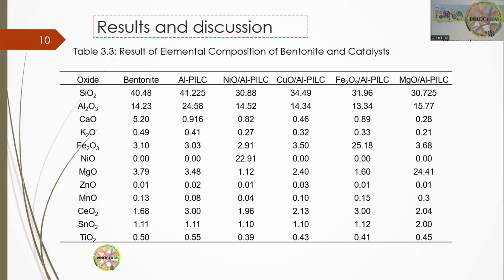This is the elemental composition of the bentonite and all other catalysts. Aluminum oxide and silica, which are the main constituents of the montmorillonite, have been observed. Then we have calcium, which is about 5.20. Because of that, we don't even have the presence of sodium, so we classify this bentonite as a calcium bentonite. And the high percentage you are seeing in nickel is because of the 20% nickel we added onto the aluminum pillared clay. Also, you can observe that after the addition of the pillaring solution containing aluminum, the amount of aluminum oxide has significantly increased compared to the other samples.